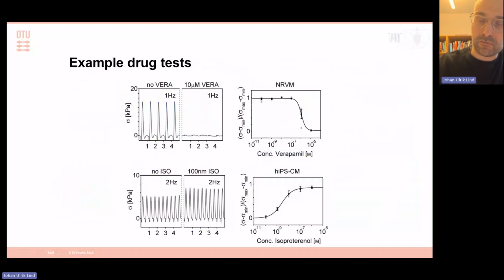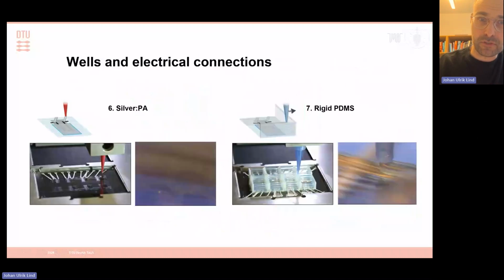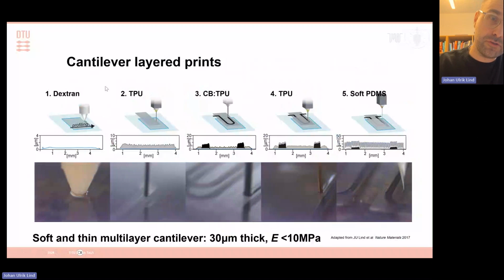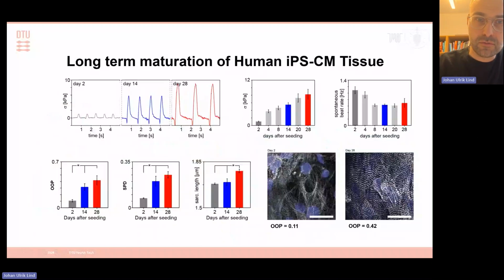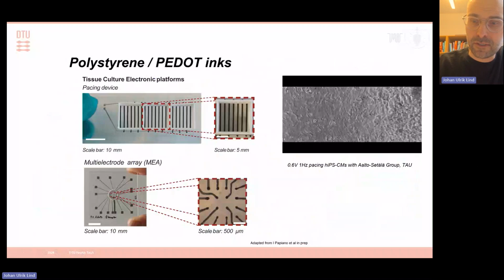One of the things that wasn't ideal with this system that I'm showing here is that for thermoplastic polyurethanes, you typically rely on polar solvents that tend to have a high toxicity. So that would be something like THF or DMF as a carrier solvent. So we were interested in looking at alternatives.